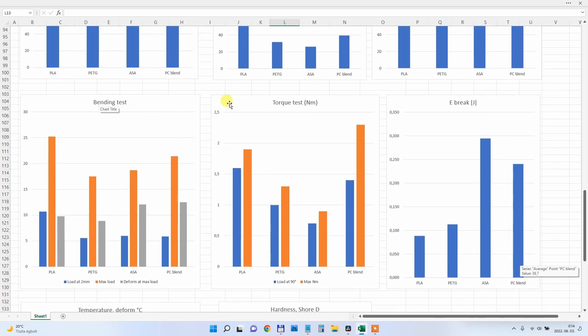Now, usually on bending test and torque test, I got very similar results. And if I watch only the first 2 millimeter deformation and the 90 degree deformation, I have very similar results, except here. So the PC blend was weaker, but the maximal bending load was a little bit better.